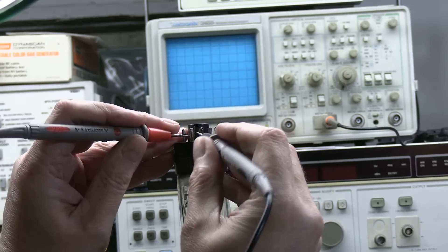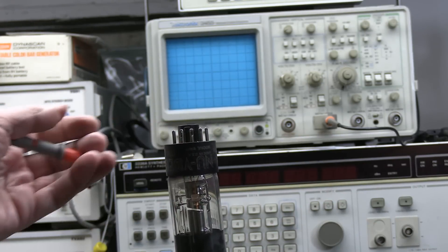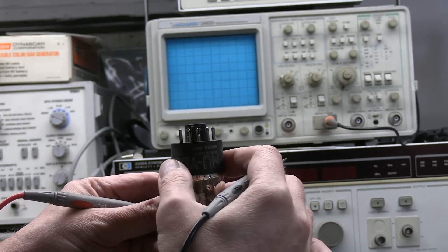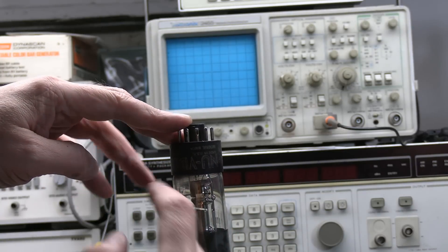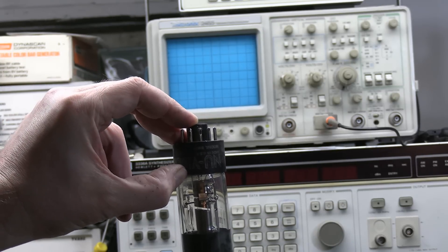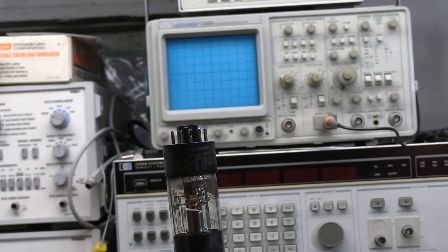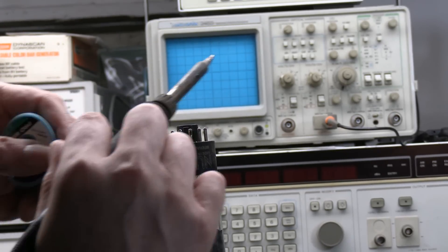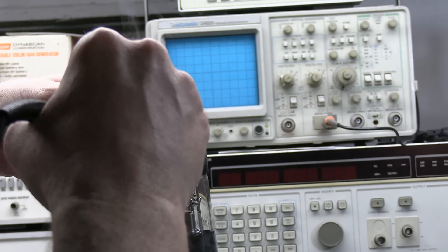We can take it a step further and we can bust off this base and get to the actual wire. There is one other possibility. The wire could have broken inside here. That would be far more likely if this base was looser. It's a little bit loose which will make it easy to get this off, but if it was really loose and it had gotten twisted, there could be metal fatigue. I have encountered one CRT where the wire broke off right at the glass, and I was able to expose enough metal on the little stub and solder a lead to it and resurrect it. However, it's not for the faint of heart and it's not guaranteed to work. So now I'm going to get some desoldering braid and put it right on the ends and try to get out all the solder so the base should just lift right off because the glue seal is already broken on it.